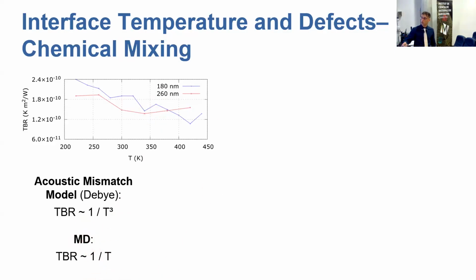In contrast with the simplest phenomenological model, which can be found in literature, these semi-analytical models predict basically a dependency which would go like temperature to the power -3, which basically comes from the Debye T-cubed law of specific heat.